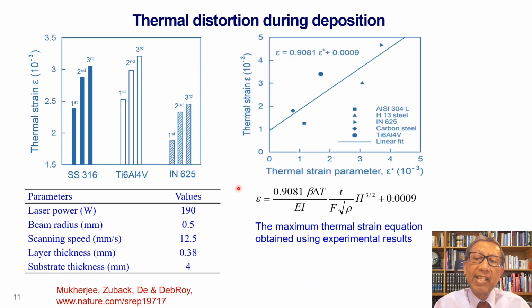For a given set of process parameters, such as the ones given here, the temperature fields, the fusion zone dimensions, and the heating and cooling rates will depend on material properties. As a result, strains will be different for different parts made with different alloys, and this is what is shown here. Stainless steel 316, Ti 64, and Inconel 625, they show different extents of strain.